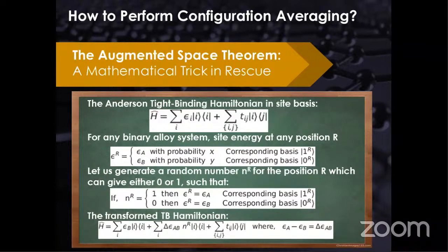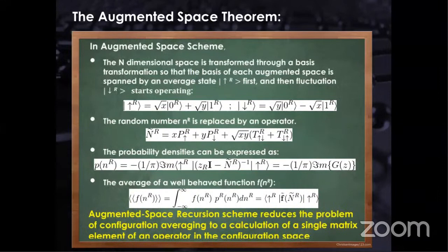This starts with the tight binding Hamiltonian, and each site can have either A or B type of atom in a binary system. In a ternary system, there are A, B, C, and something like that. And what we do in this is take a random number which can take either 1 or 0. If at any site it is 1, then it is occupied by A, and if it is 0, then it is occupied by B. This is the very starting point of this, and then we do a basis transformation. Basically, when we are talking about an n atom system, this is an n dimensional space, and the basis are the atomic basis.